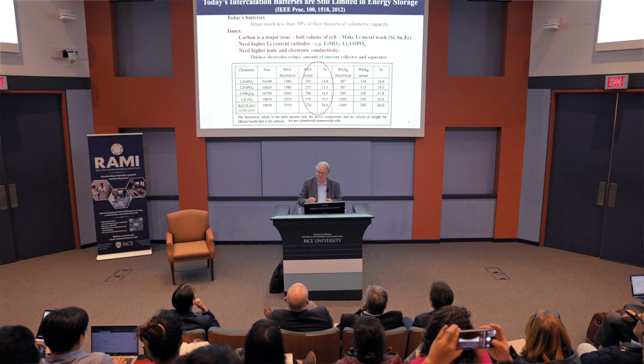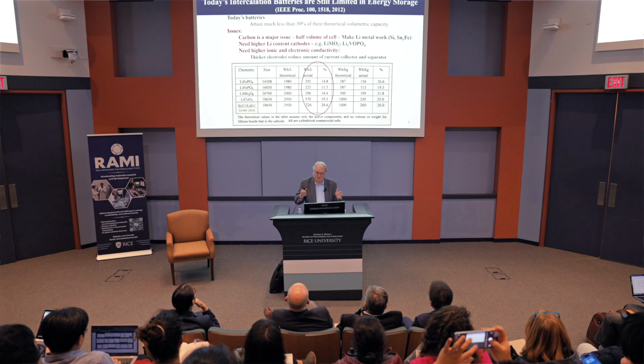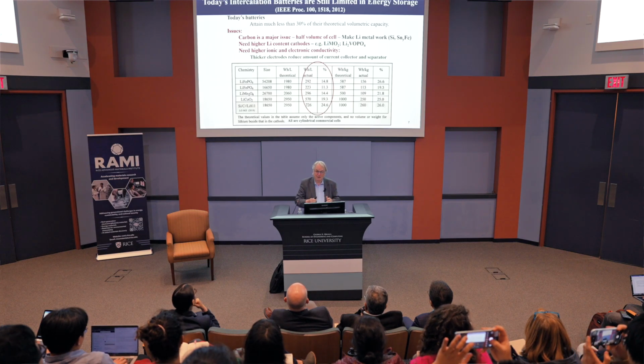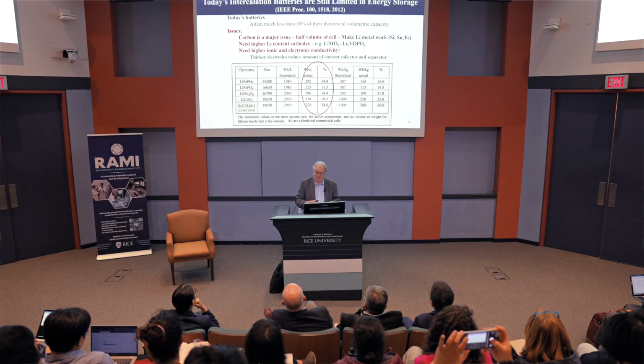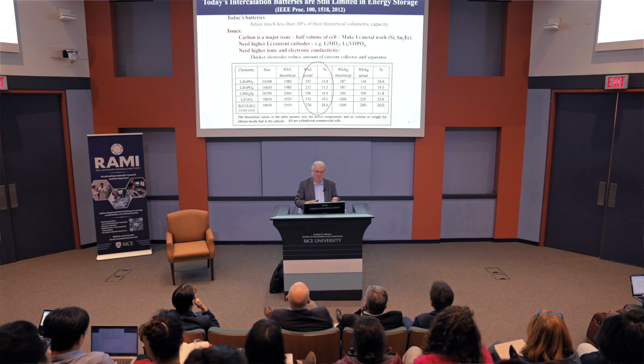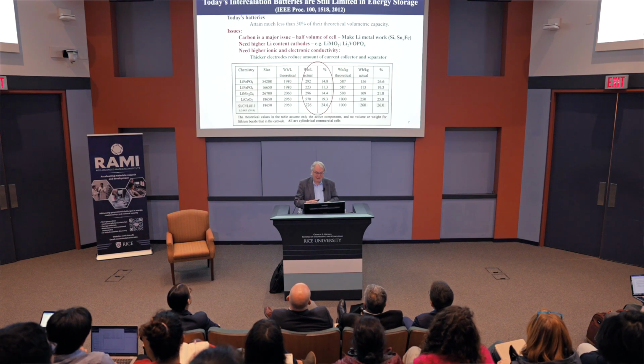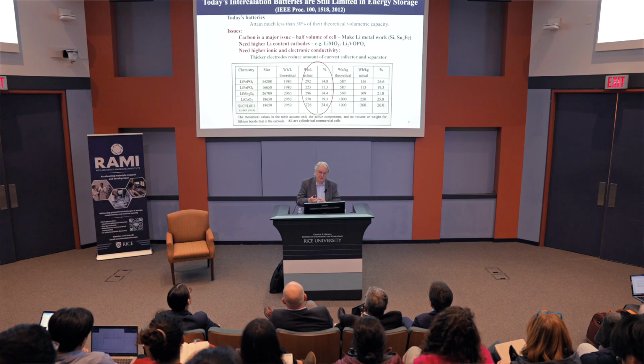So there's a huge opportunity for us to increase that. Now, you can't go all the way to 100% because you've got electrolytes there, you've got casings and everything else, but we can increase it. And the issue I already mentioned, the carbon takes up half the volume. It takes up a lot of weight. It has to go. We need to put more lithiums in per transition metal. That'll increase it. And we need materials that have better electronic conductivity and ionic conductivity. Because remember, if you move ions in and out for a battery, you're moving electrons in and out. Many of these are not good electronic conductors.